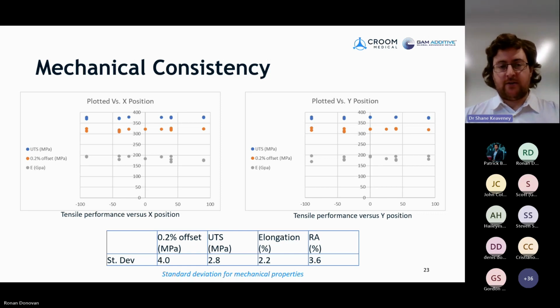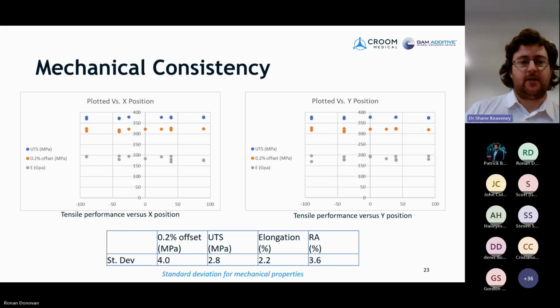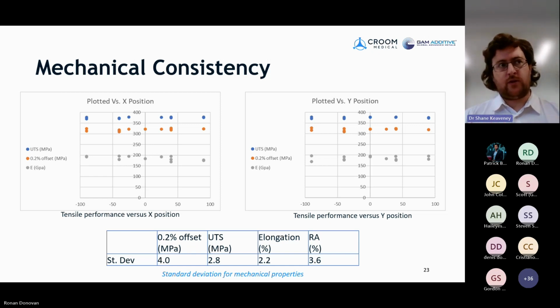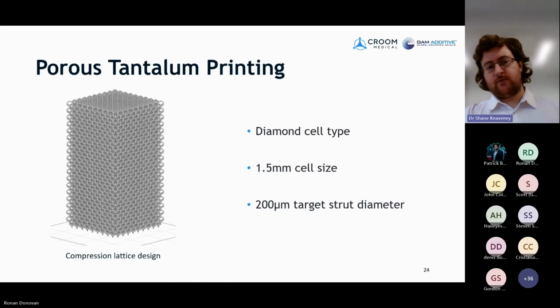Moreover, if I look at the standard deviations for proof stress, UTS, elongation, and the reduction in area, again, you see these are quite low. So quite consistent for elongation as well, which is very good because elongation is a little bit more sensitive due to the nature of how a failure happens during tensile test. It takes a very minute defect on the sample that might change the elongation between 2 samples. So quite good to see. So that's in terms of our solid.